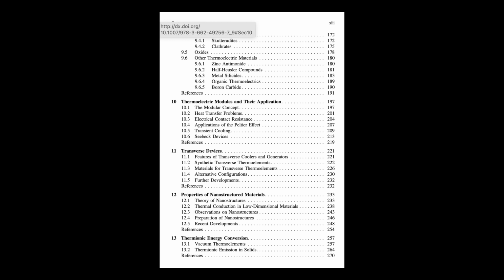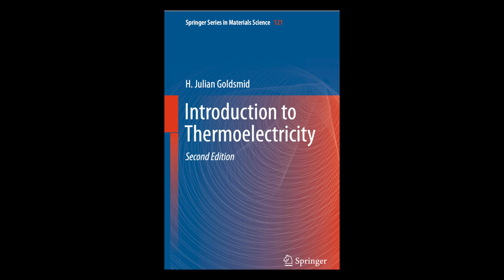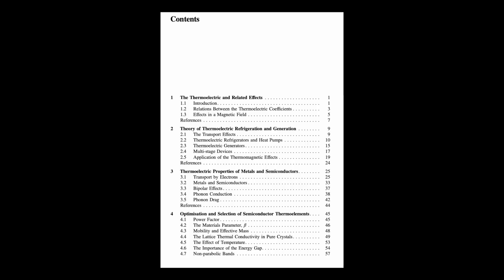Okay, interesting trade-off. The outline then brings in this material's parameter, beta. What does that represent? Beta is a kind of fundamental indicator of a material's inherent thermoelectric potential. It bundles together things like carrier mobility, effective mass, how carriers respond in the crystal, and the lattice thermal conductivity. And this beta is directly linked to the dimensionless figure of merit, ZT, which is our main performance metric. Basically, higher beta means higher potential ZT. The exact link also involves that scattering parameter we mentioned.